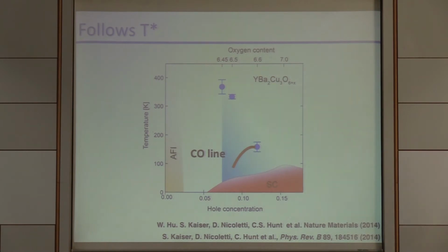This is my point. So this is the light-induced plasma edge, which in this case is the result of a mean field fit, because we can only measure up to 300 Kelvin, and we haven't heated too much. But let's say that this is our best guess of where this light-induced TC-like fit disappears. And we can see it follows something that is similar to this mysterious T-star line.